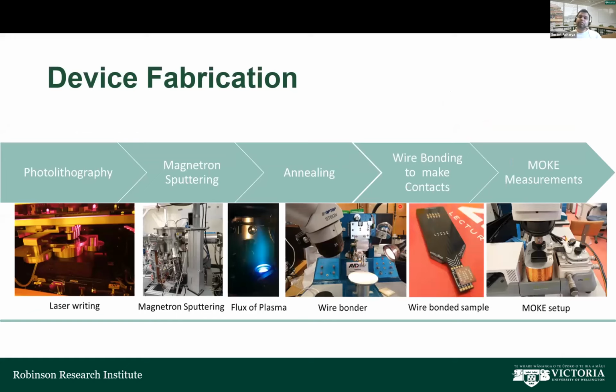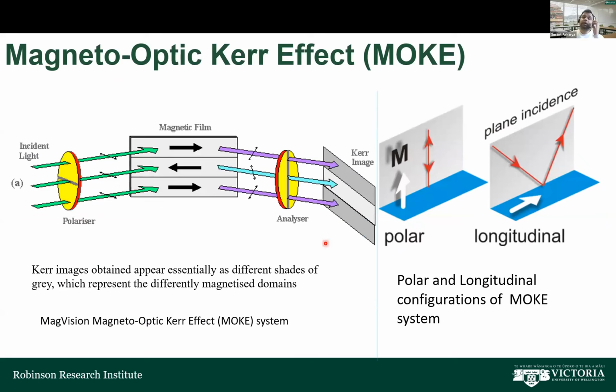For this purpose, we mostly use photolithography and a high vacuum deposition system to deposit the thin film stack. Then we annealed at 300 degrees centigrade, and the characterization was mostly done using the magneto-optic Kerr effect, MOKE. Most of you are familiar with the magneto-optic Kerr effect, but basically, we put polarized light on a magnetic thin film and analyze the reflected light, and based on the spin orientation of the thin film, we get image contrast.